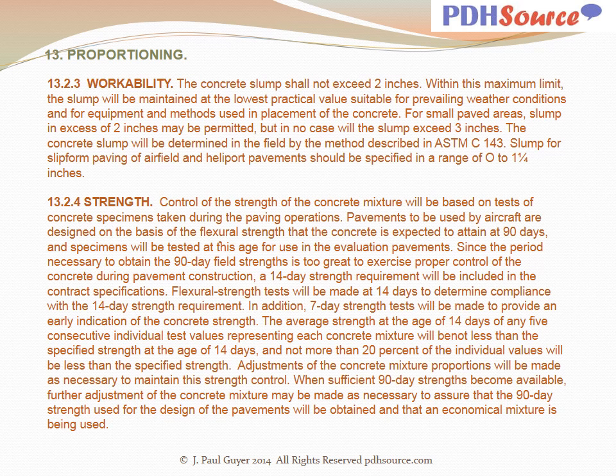Control of the strength of the concrete mixtures shall be based on tests of concrete specimens taken during the paving operations. Pavements to be used by aircraft are designed on the basis of flexural strength that the concrete is expected to attain at 90 days, and specimens will be tested at this age for use in the evaluation of pavements. Since the period necessary to obtain the 90-day field strength is too great to exercise proper control of the concrete during pavement construction, a 14-day strength requirement will be included in the contract specifications.